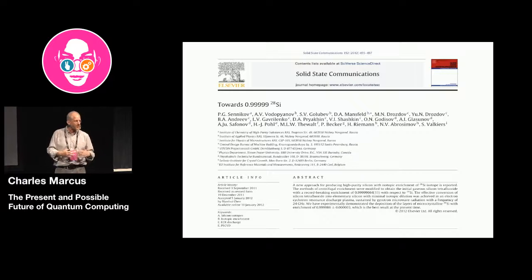They specifically picked materials that didn't have nuclear spin. Now interestingly, a material that everybody here is familiar with, silicon, silicon is a material that doesn't have any nuclear spin. Well, actually that's not quite true. Silicon 28, the predominant species of silicon, and germanium is the same story, is mostly, silicon 28 is nuclear spin zero. Great, so at least that problem won't exist. But there's this residual 4% that's silicon 29 in naturally occurring silicon, and those spins were enough to cause the problem. So when people moved to a silicon-silicon germanium quantum dot to do these experiments later, same problem from the residual 4%. So then came a whole community of people who were interested in trying to produce 99.9999% pure silicon 28. Now you'll notice the nationality of a lot of the authors of this paper, and these were the communities that used to be spinning plutonium in their centrifuges in the Soviet Union. They're now in the business of purifying silicon to make quantum computers, and other applications as well.